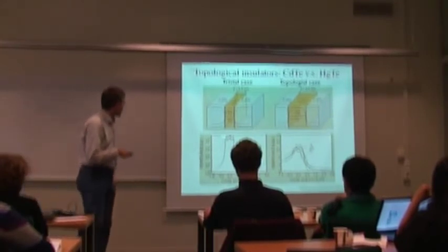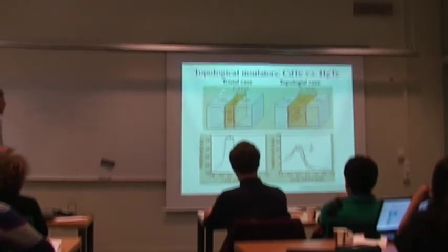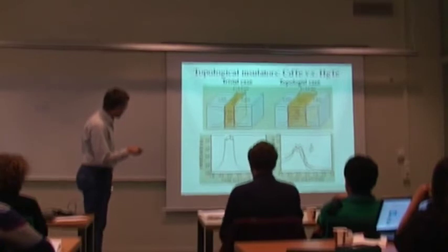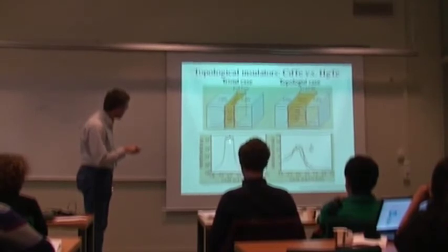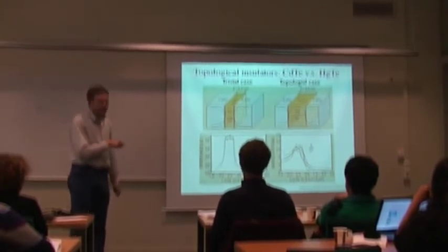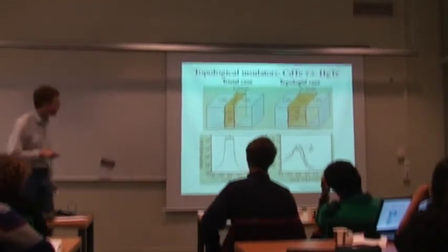They did these measurements and measured some resistance. In this case, where the layer is very thin, I'm not going to explain the details of the setup, but this is the region of gate voltage you have to focus on, where they're really probing these interfaces. There you see that the resistance gets really high. It just shoots up to some value, and then they cannot measure it any higher. They're limited in their measurements. This is for the thin layers.